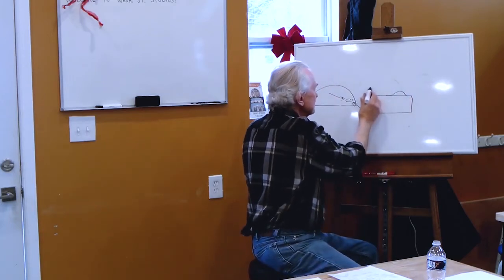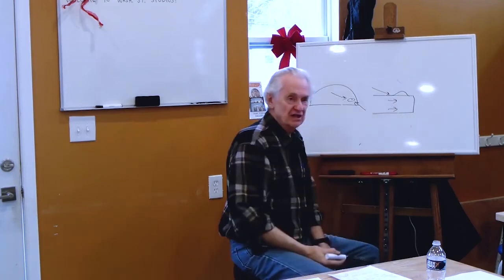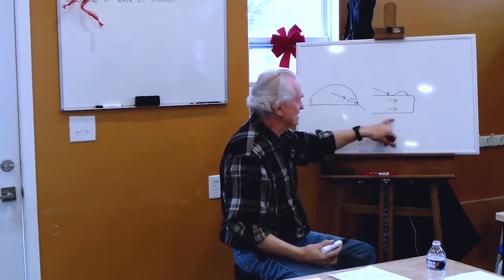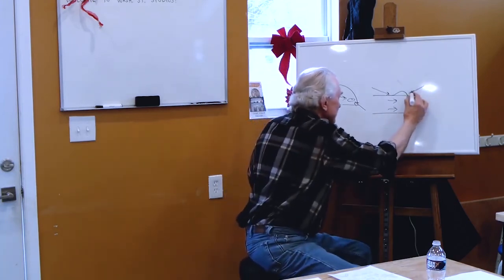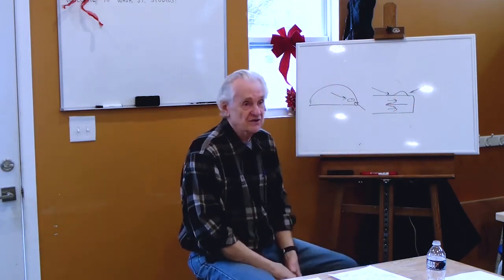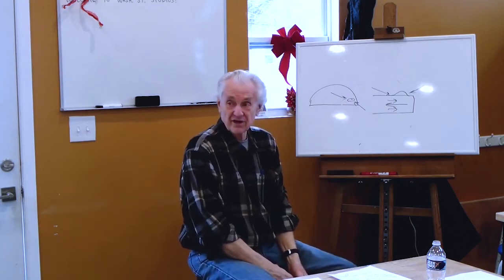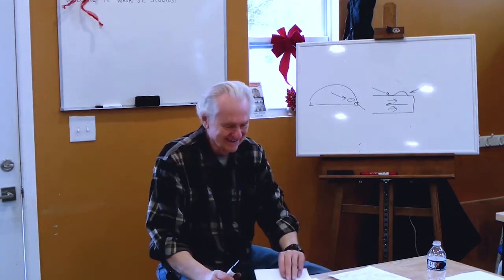If I have a chisel and I hit the glaze drip this way, I'm putting tension on the whole shelf. Well, again, that's why I can knock that corner or that edge of the shelf off. Whereas if I hit it this way, I'm still going to flake the glaze off, but now I'm putting the shelf under compression, and I won't knock the corner of the shelf off. That's the reason why it's recommended. Maybe you don't do it, but you should. Okay?